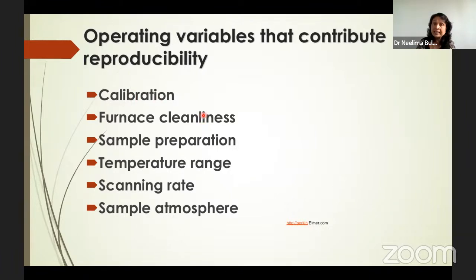Second thing is furnace cleanliness. Sample preparation is extremely important, because if you have a non-conducting material, and you keep a chunk of that material in your TGA sample holder and heat it, your heaters are sitting at the bottom of your sample holder. If your sample is heated only from the bottom, and you are keeping a chunk of around, let's say, 7 to 8 mm height, then there will be a temperature lag in the sample itself, and you will not get the correct result. So sample preparation is extremely important. And of course, the temperature range of interest.